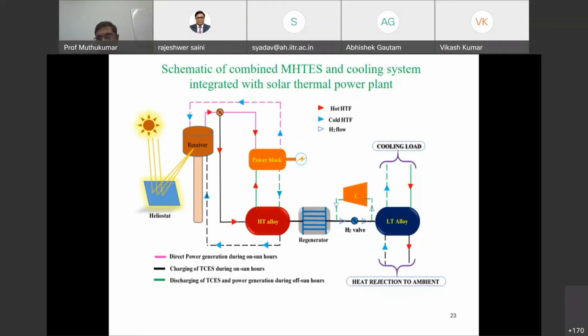You are supplying heat to the metal hydride system during the charging at about 350 degrees Celsius. During discharging, you are getting two outputs. One output is from the low temperature alloy, you are getting the cooling at about 10 to 15 degrees Celsius. In addition to this cooling, you will be getting the upgraded heat output at about 450 degrees Celsius.